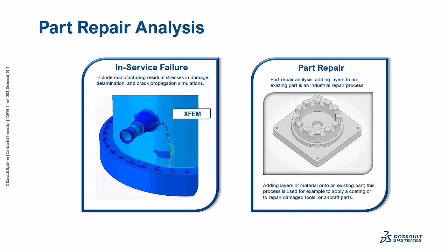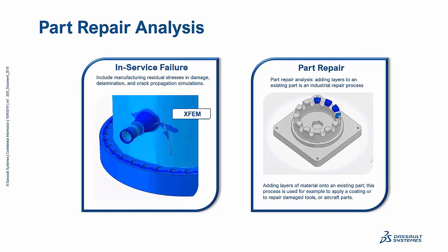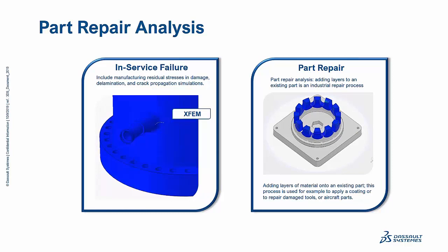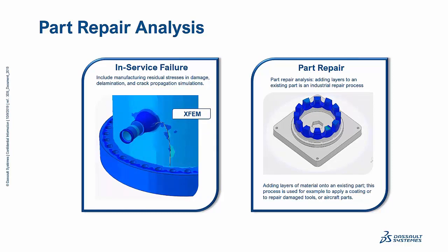We talk about print to perform, and performance even affects the part after the print process. We see here in this example an in-service failure where the part cracks after the print process in a service situation. And again, it is highly dependent on the existing residual stresses in the structure. On the right-hand side of this simulation, we can see a repair simulation. So the colors here represent the temperature field. Again, this is only possible in thermomechanical analysis.